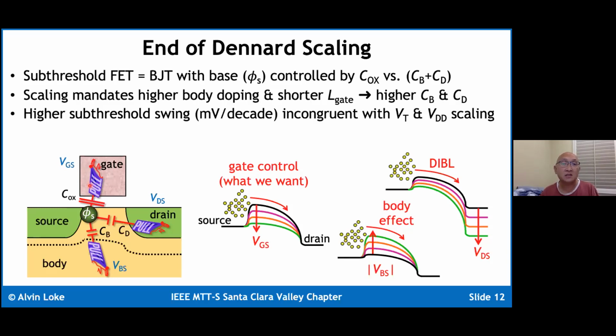Okay, and so what that means is that, as you've seen, when we try to scale to shorter and shorter gate lengths, body dopings have gotten higher and higher, which has made the depletion region thinner, which means that the body coupling and the drain coupling becomes stronger, which works against you. So you've got a capacitor divider, which basically works against you. You really want CB and CD to be zero. You want COX to be fully controlling, tightly coupling the gate to the surface potential. And so the net result is you're going to get a higher subthreshold swing, which means you need more change in gate voltage to induce several decades of transistor current. And so when we're trying to scale the supply for lower power, we're trying to scale the VT, obviously this higher subthreshold swing is not working in our favor.